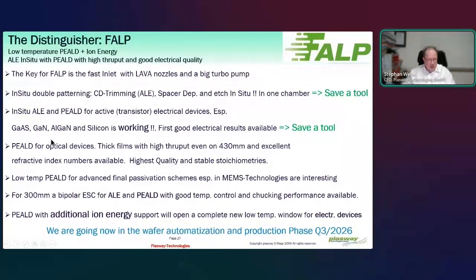And we can also do PEALD for optical devices. Even 500 nanometer thick films are possible, even on 430 millimeter substrate. And we can do this 500 nanometer within 2 or 3 hours. So therefore, we are really on the way to develop a tool, or have already developed a tool, where you can also work in back-end processes, so the temperature is not so high. And this is also just possible due to the fact that we have a very good temperature control via a bipolar e-chuck. And we open up a complete new window with additional ion energy, with an additional kinetic energy to create polycrystalline and maybe also crystalline material.